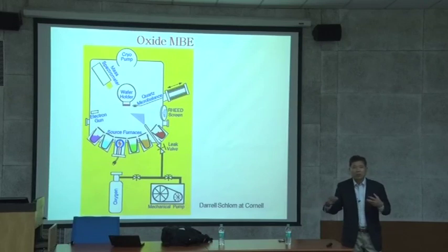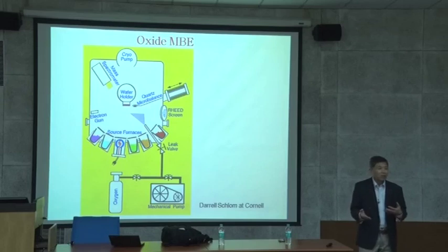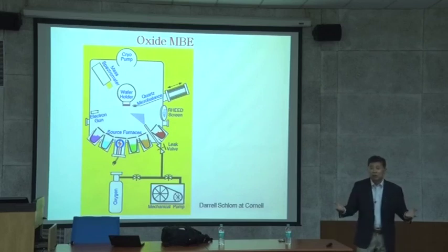And that allows you to grow strontium titanate epitaxially on silicon, and we'll talk about that next week. Because when you grow this on silicon, the silicon immediately oxidizes, forming an amorphous SiO2 layer. So in order to overcome this, they have to use a strontium layer first. If titanium goes first, then titanium silicide forms, which is not ideal. So what kind of element do you touch first? That's the way you have more degrees of freedom you can play with.